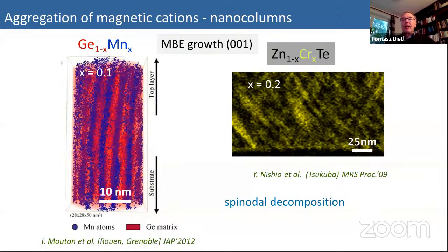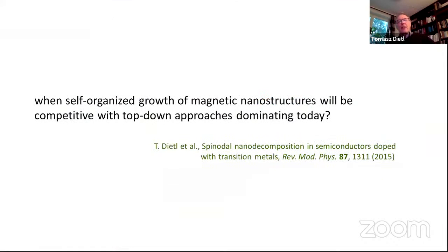the growth direction. The same you can observe in the case of zinc chromium telluride. This time, these nanocolumns grow along the 1-1-1 direction. And we call this phenomenon spinodal decomposition: again, we have a beautiful zinc blende structure here, but locally, using chemistry, we see that there is aggregation of chromium atoms in the form of nanocolumns. Of course, you can have many different shapes, and you can ask a relevant question: when and to what extent will the self-organized growth of magnetic nanostructures be competitive with top-down approaches dominating today? So probably at some point it concerns spintronics, but it also may concern electronics, that we dream about self-organization instead of top-down methods which are dominating today.